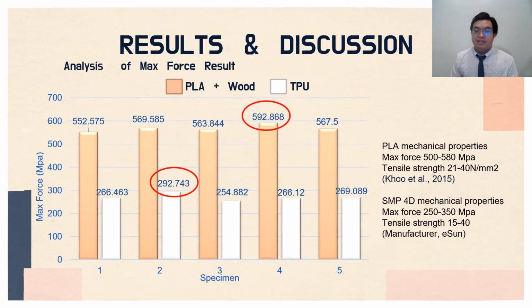Continuing with the result and discussion on the analysis of max force results. From the bar chart that has been produced, it showed 592 megapascal for the PLA plus wood before it breaks, and the max force for the TPU is 292 megapascal. Compared with the previous study by Khoo et al. in 2015, the max force needed for PLA is 500 to 580 megapascal, and the max force needed for the smart material polymer is 250 to 350 megapascal. It shows that the part printed in this project is still in the range of the max force result.